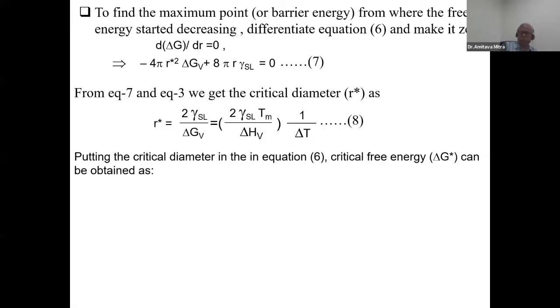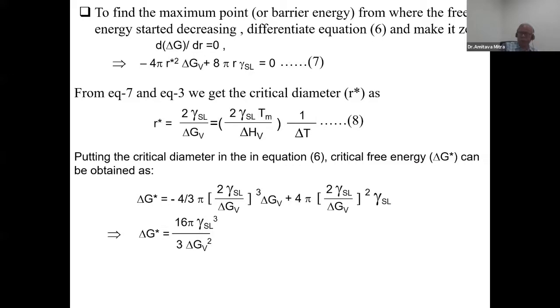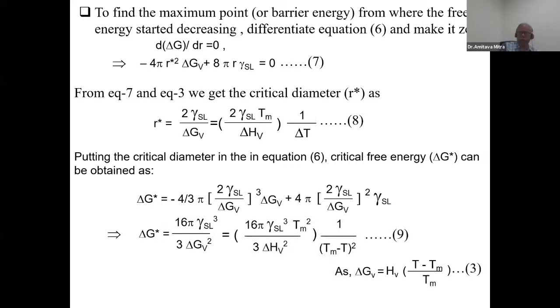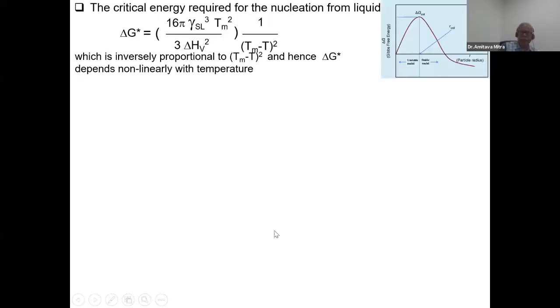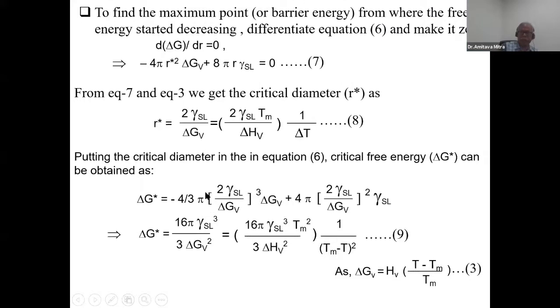That is T minus Tm. So putting this critical diameter in the above equation, we ultimately get an equation giving delta G star, the critical Gibbs free energy, which is inversely proportional to Tm minus T whole square, that is delta T whole square. What is delta T? That is Tm minus T.